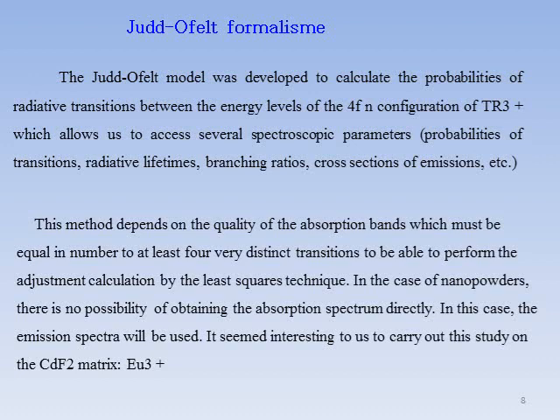To perform this study, the results of luminescence and lifetime measurements were analyzed. The Judd-Ofelt intensity parameters were investigated using the data taken from the luminescence spectra, which allowed evaluating the transition probability, radiative lifetime, and as final results the emission cross-section and the quantum efficiency of the europium in CdF2 single crystal. The Judd-Ofelt model was developed to calculate the probability of radiative transition between the energy levels of the 4f configuration of europium ion, which allowed us to access several spectroscopic parameters.